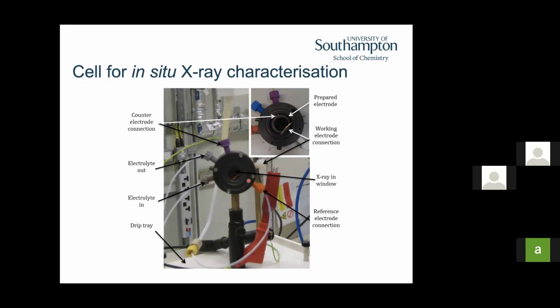So we pump the electrolytes in and out, which means that we can circulate the electrolyte, and then our reference electrode comes in here. So that's not ideal, but it allows us to use a proper reference electrode on the beamline. You could put, say, just a palladium bead that you charge with hydrogen to make a palladium hydrogen reference electrode. You could just have platinum wire in there and have a platinum pseudo-reference electrode, but we like to use either a mercury sulfate or an RHE electrode.